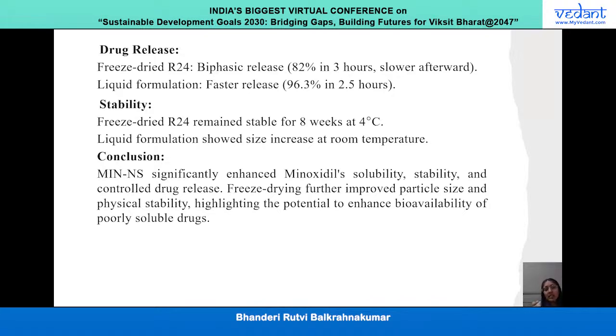Stability: freeze dried R24 remained stable for 8 weeks at 4 degrees Celsius. Liquid formulation showed size increase at room temperature. Conclusion: this combination significantly enhanced minoxidil's solubility, stability, and controlled release. Freeze drying further improved particle size and physical stability, highlighting the potential to enhance bioavailability of poorly soluble drugs.